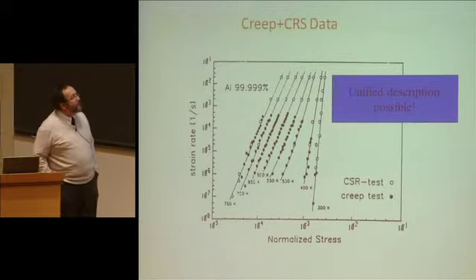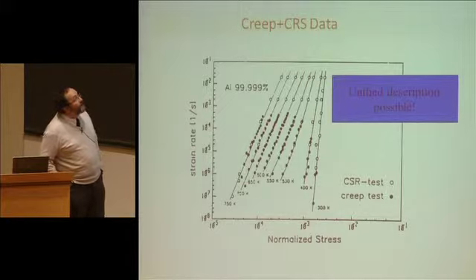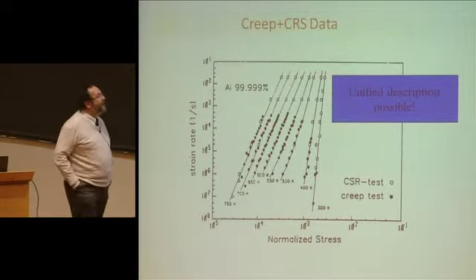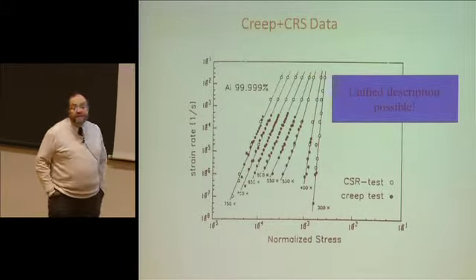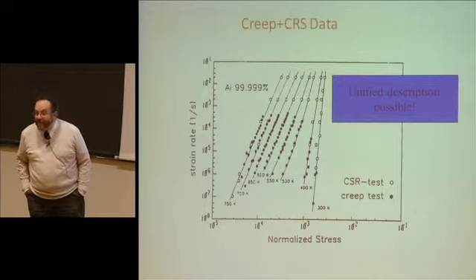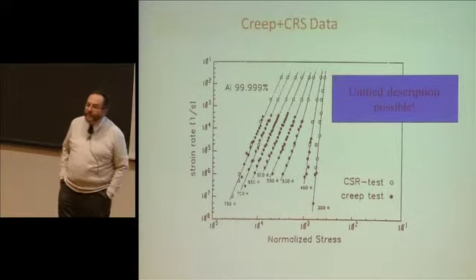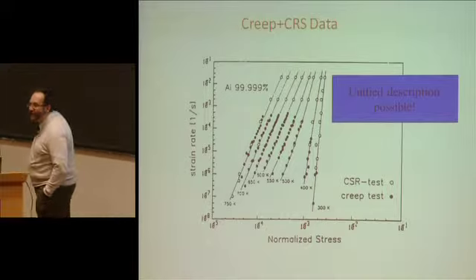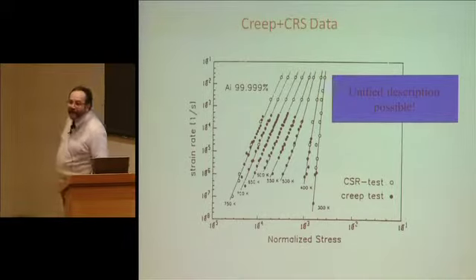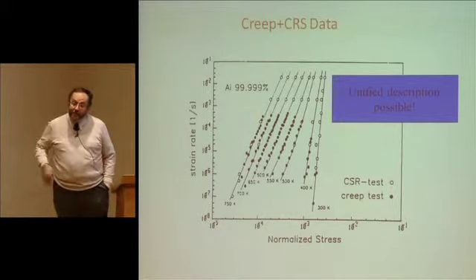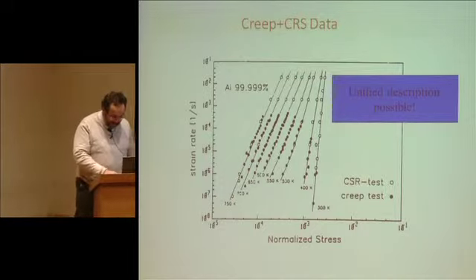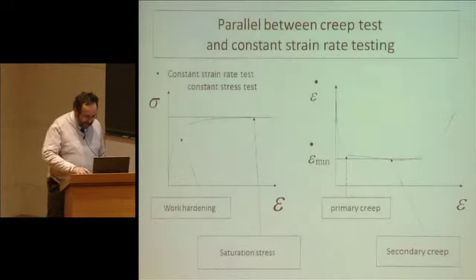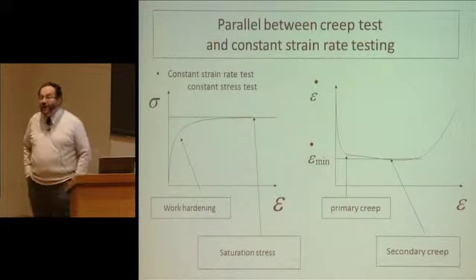The creep tests are the full ones, and the other ones are the hollow ones, and essentially they are actually quite well aligned. So at least in these scales of temperatures, there's no real reason to believe that you have different types of deformation. And it's not always the case, but it was here.